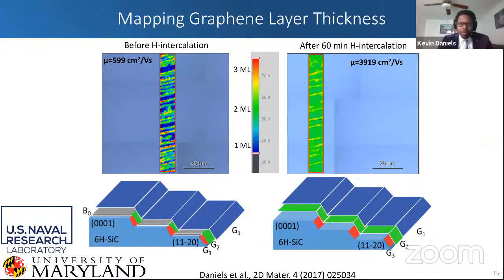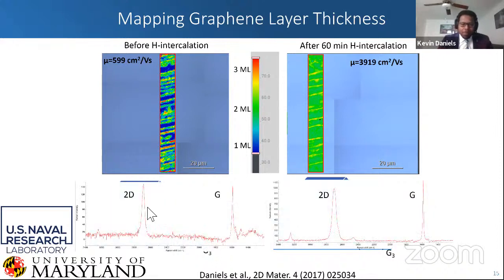And so this is just showing layer thickness. So again, 1, 2, and 3 layers. This is done by Raman spectroscopy, which basically looks at the phonon vibrational modes. And from a peak called the 2D peak, we're able to see that we have an additional layer formed from the promotion of that buffer layer. And so this is the same substrate that we've intercalated, and you see a huge improvement in the carrier mobility as a result.